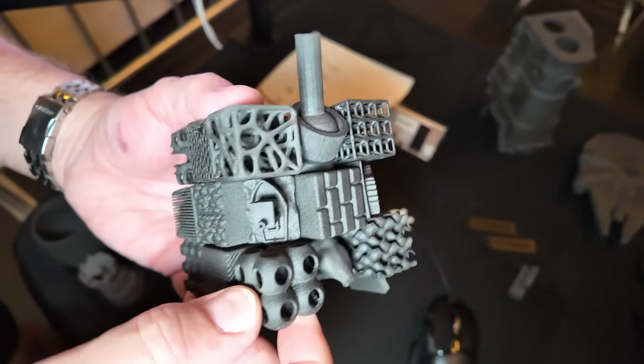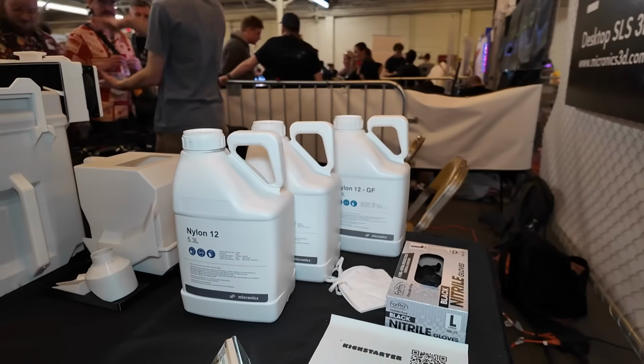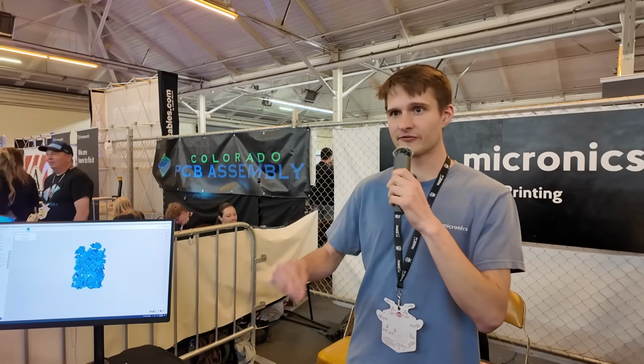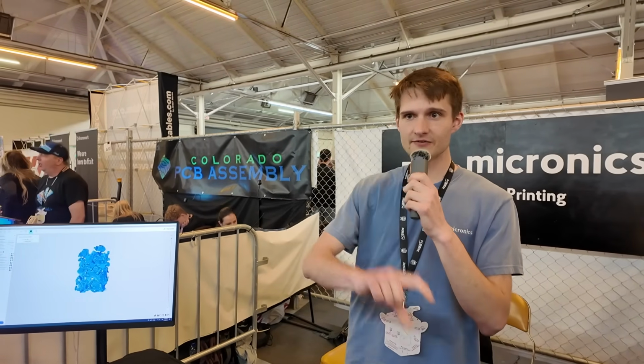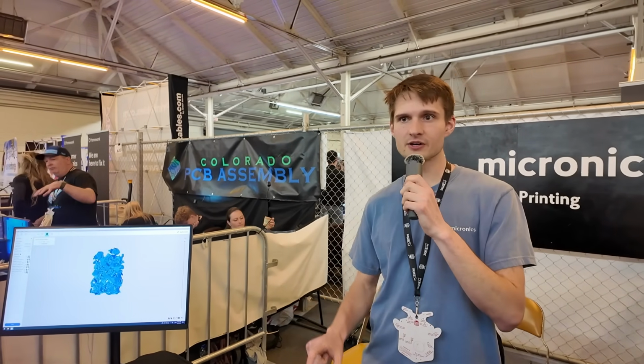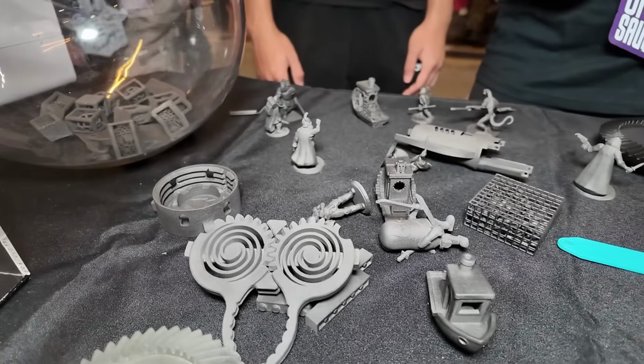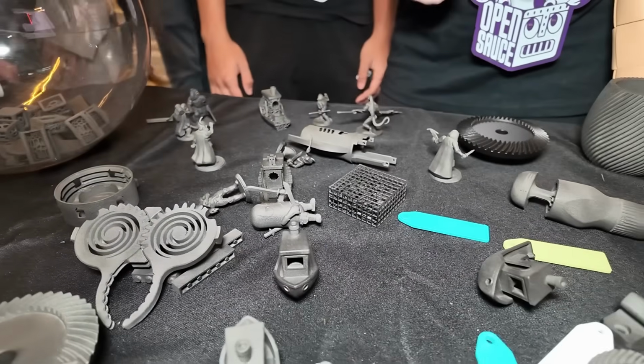The design freedom of SLS 3D printing and the self-supporting nature of the powder is great, but it also comes with a problem not many really talk about. So there's a bit of degradation just from the thermal cycling of the material, and there is also some particles will fuse together. So this means that you can't indefinitely reuse your powder. You always need to mix in a minimal amount of new powder in order to reduce the degradation effect. We recommend a refresh rate of 30%, so that's 70% used and 30% new powder. You certainly can use more used powder. We've tested as low as 10% and it prints just fine.